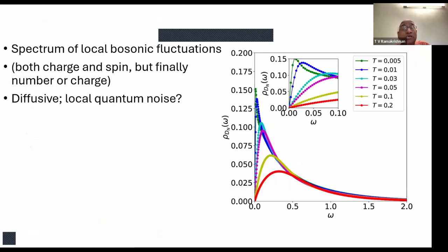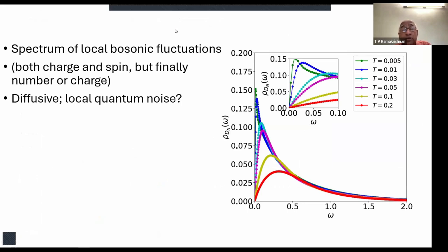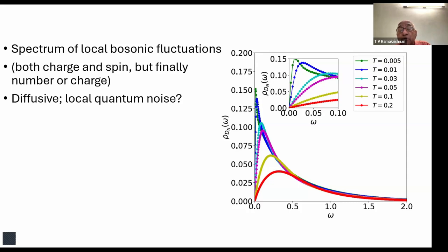If I have the next slide, I can show more. While obtaining this result, we found that there are inevitable local bosonic fluctuations of local charge or local spin with which the electrons are coupled. I have shown here the spectrum of local bosonic charge fluctuation at a doping of, I think, 2 or so, for different frequencies and temperatures. You see, at the lowest temperature, it's extremely sharp. As the temperature increases, this bosonic fluctuation becomes somewhat broader. It is highly asymmetric. It has a sharp rise followed by a rather broad, gentle decay.